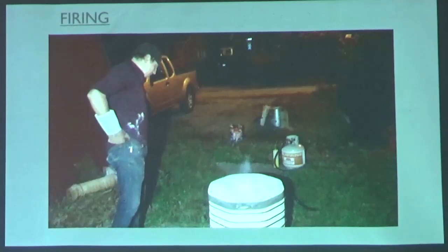So I'll fire them, take them out, cover the kiln back up, and when I go back to put a new piece in that has slip just freshly poured on it, the kiln is at 1200 degrees already. So it only takes 15 minutes to get back up to 1600 degrees or so. Okay. And how long then do you leave the piece in the kiln? Once it hits that 1600 degrees, I let it soak for about a minute, 2 minutes, let it really come up to temperature, and then off with the lid into the fire. So maybe about 20 minutes total from the time you put it in. Yeah. And of course the first piece takes about 40 minutes to get up to that temperature. But after that it's a lot faster. Obviously the kiln has done most of the work already, so it just has to get reheated.